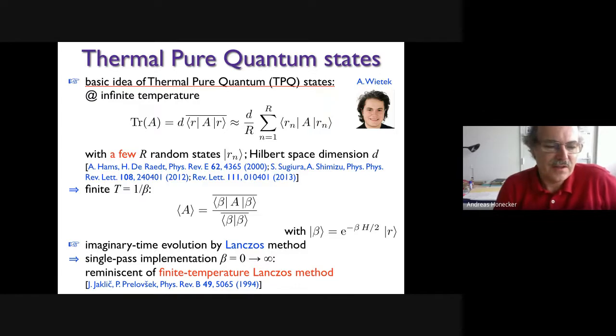So with that, you can then do thermodynamics for a bigger system, and here I'm showing you now results up to 40 sites at the ratio relevant to strontium copper borate. This is going up to 40 spins with typically 5 vectors for 40 spins. What is a bit funny is that you get error bars on exact data. This is because of the sampling.